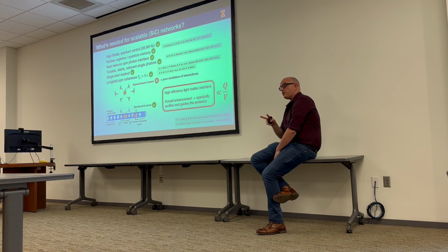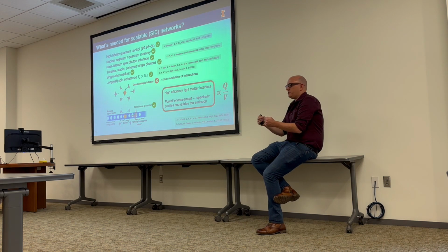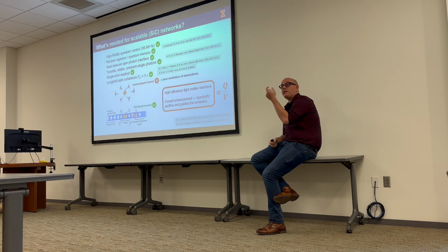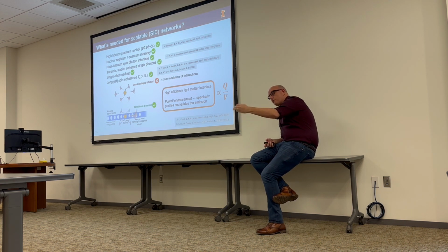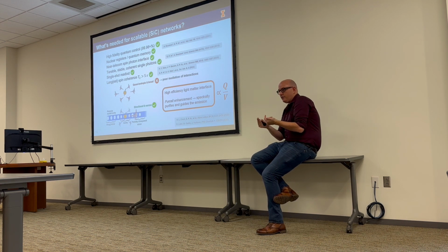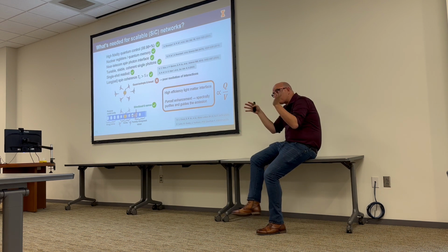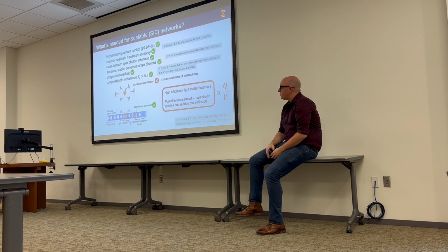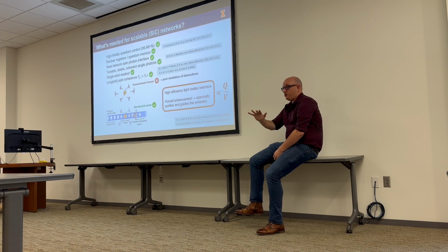So there's two things here. One is we have this two-level system. We bring it up to the excited state, it radiates light. Problem is it doesn't do that immediately. It has some lifetime that it lives in that excited state. So sometimes it radiates immediately, sometimes it takes 10 nanoseconds to radiate, and there's a phase difference there. And so your wave packet has some very particular shape, the spread of all those phases giving you some 10 nanosecond wave packet. So that fundamentally we can't change, we can't get around.